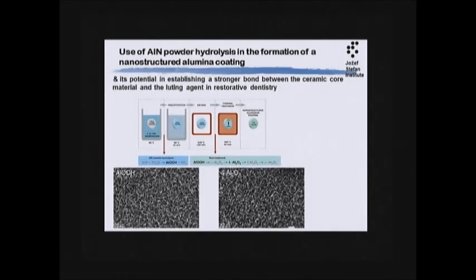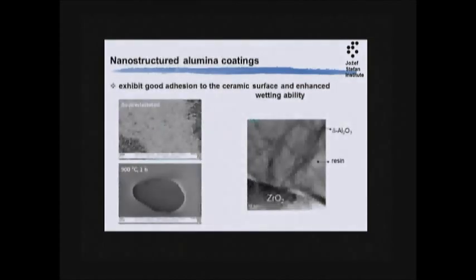And if you heat that up, you will first lose the chemically bound water, and then you'll go through the whole sequence of transient aluminas: gamma, delta, theta, up to alpha. Alpha is at 1150 degrees C. But we stopped before that. After deposition of this layer, the adhesion of the layer to the substrate is very weak. You can remove it by a Scotch tape, but after a heat treatment, 900 degrees C, you get the opposite situation. This is the glue, so you remove the glue from the tape. The coating adheres very strongly to the surface.